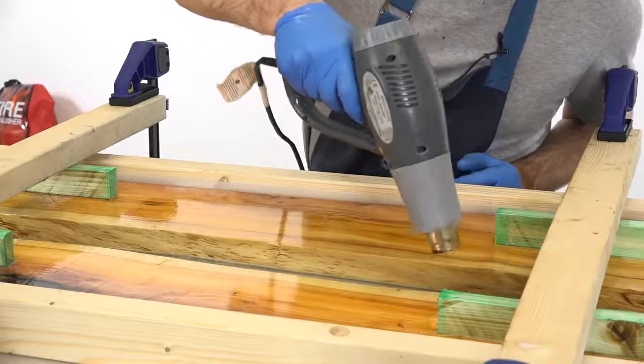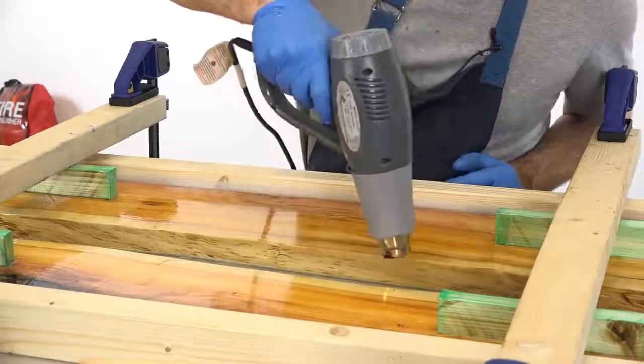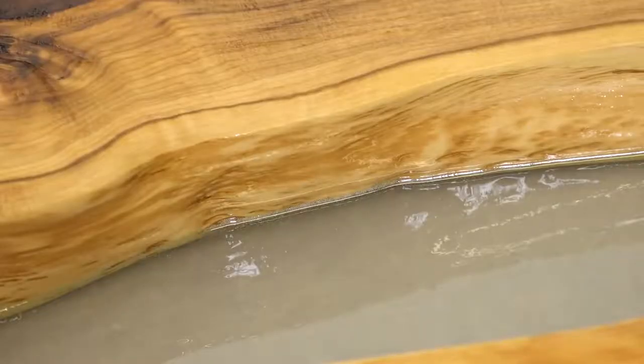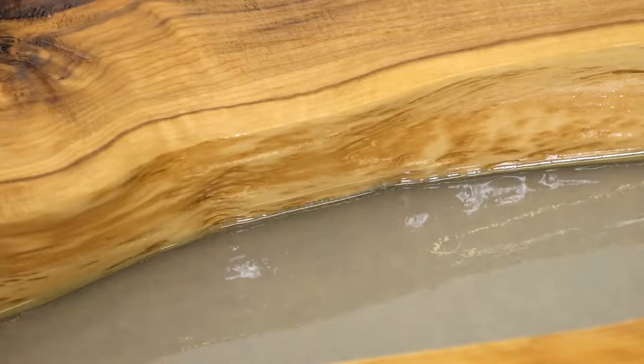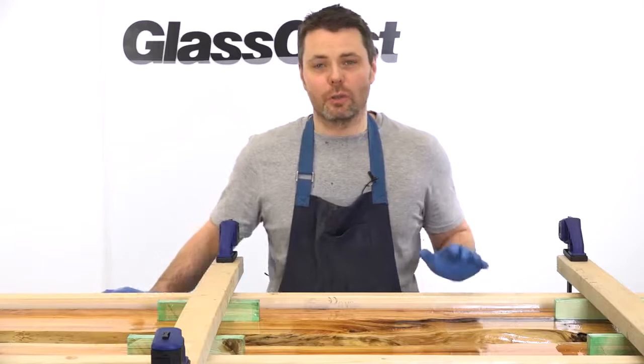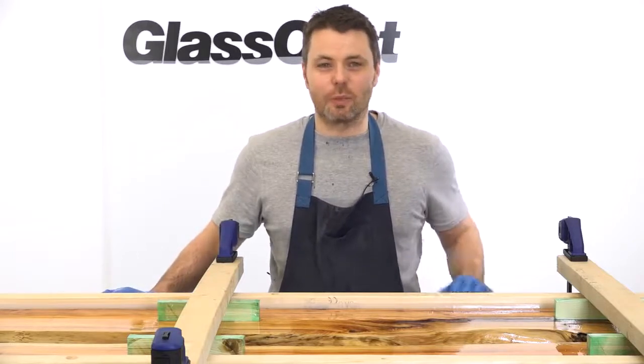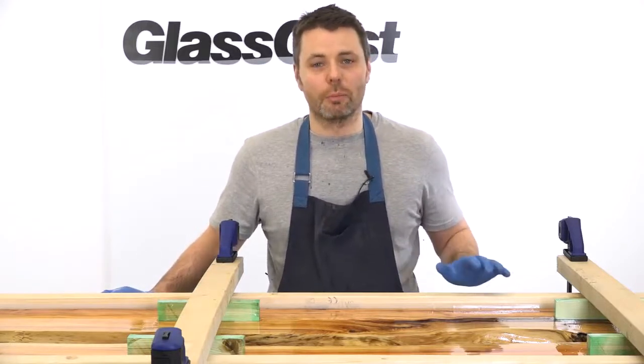Glasscast 50 is very good at releasing trapped air without any help, but it's still a good idea to use some light action with a heat gun to help the process along. We just need to leave this first layer to cure to what we call the B stage. That'll take around 12 hours at 20 degrees, so we'll come back to this in the morning.